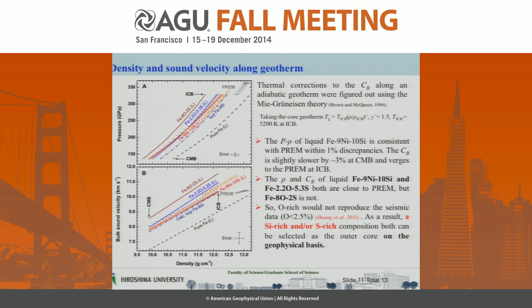For the bulk sound velocity and density relationship, the bulk sound velocity is slightly slower by 3% at the CMB and converges to PREM at the ICB. So the density and bulk sound data of our samples tell us that iron-9-nickel-10-silicon and iron-2.2-oxygen-5.3-sulfur are both close to PREM. But the oxygen-rich iron-8-oxygen-2-sulfur is not, due to the too high oxygen content. So oxygen-rich compositions would not reproduce the seismic data, and a silicon-rich and sulfur-rich composition may be selected as the outer core just based on the geophysical point.